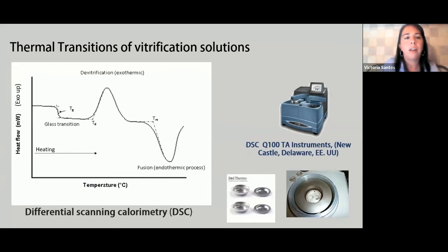Here we have a diagram of the heat flow versus temperature and the key thermal transitions during the vitrification of a sample, or of a vitrification solution, I mean. We use a differential scanning calorimeter, and we can see here that the step change is the glass transition. The onset of devitrification is Td, and it has an exothermic peak. And then we have the onset of melting with the endothermic process.